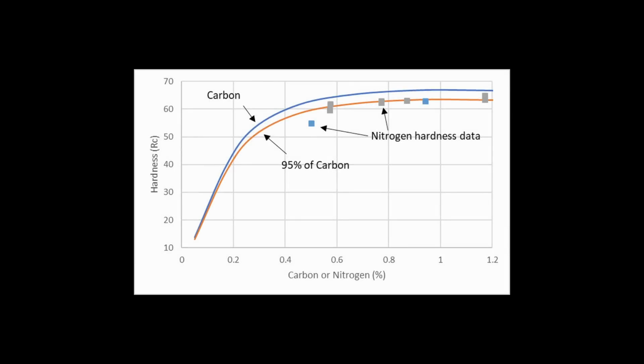But I generated a chart a few years ago that I didn't really think too much about, but I found a study where they looked at nitrogen content versus hardness in steel and then plotted it out. And then I put that on the same plot as carbon versus hardness, and the nitrogen was like 2 or 3 points softer than the carbon. And I was like, oh well, this doesn't really mean that much. I mean, the nitrogen steels I know about, they all get reasonably hard, but this will matter, as we'll see a little later.